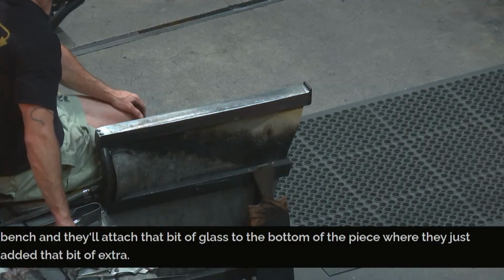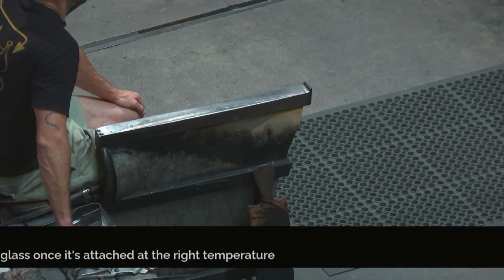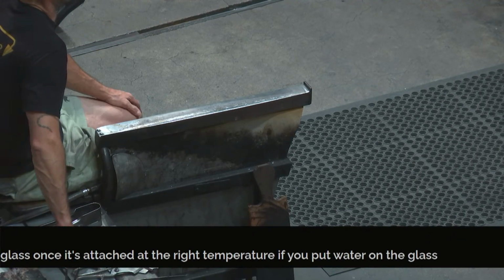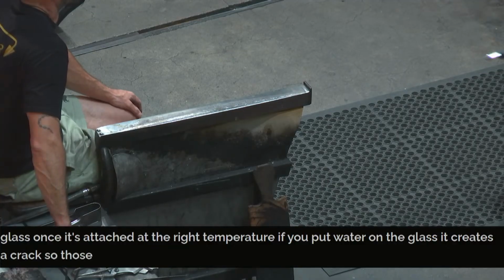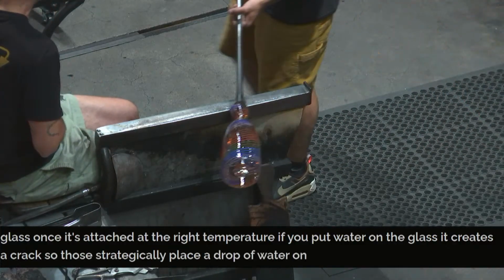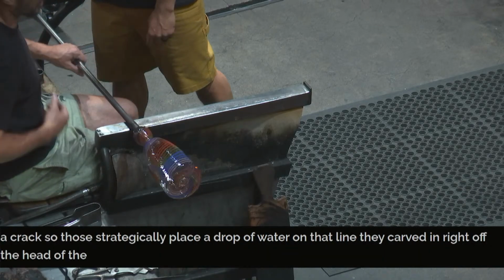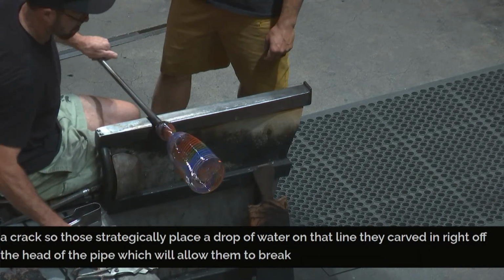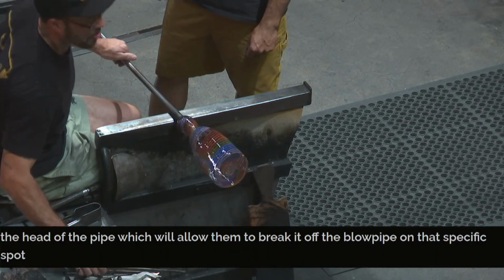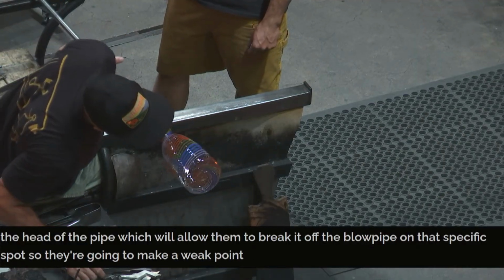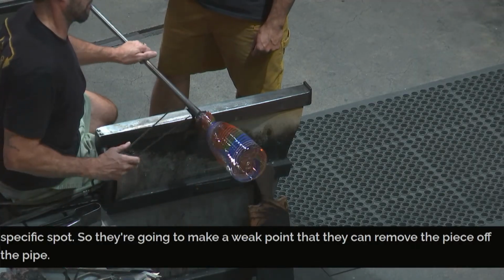Once it's attached at the right temperature, if you put water on the glass, it creates a crack. So they'll strategically place a drop of water on that line they carved in right off the head of the pipe, which will allow them to break it off the blowpipe on that specific spot. So they're going to make a weak point so that they can remove the piece off the pipe. So they're lining up their temperature.